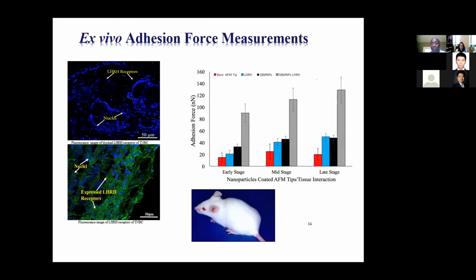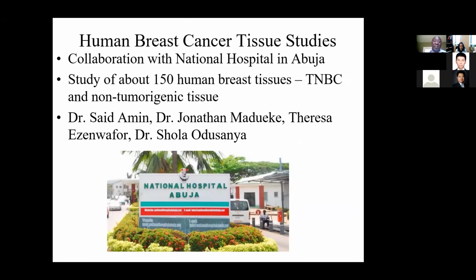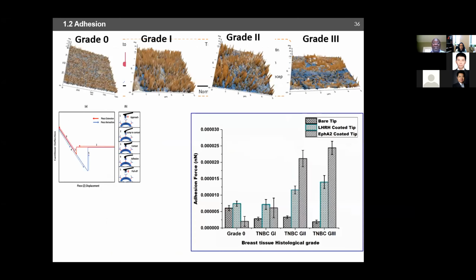of the tumor development. And you can go one step further to actually look at the adhesion in human breast tissue. And when you look at the adhesion in human breast tissues, what you find is quite interesting. So the first is you see from the AFM scans of the surfaces that these surfaces evolve as you go from grade 0 to grade 1 to grade 2 to grade 3, with some regions where you have depletion of material compared to others.